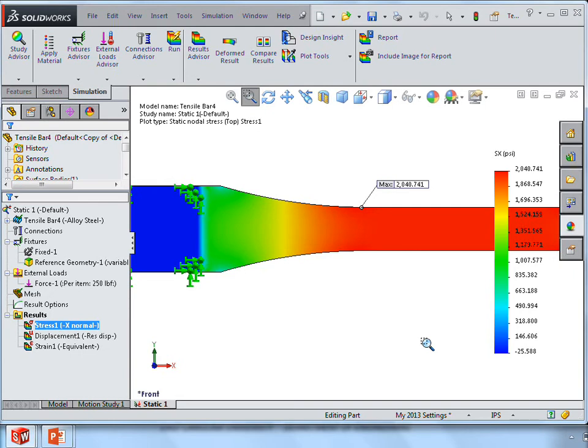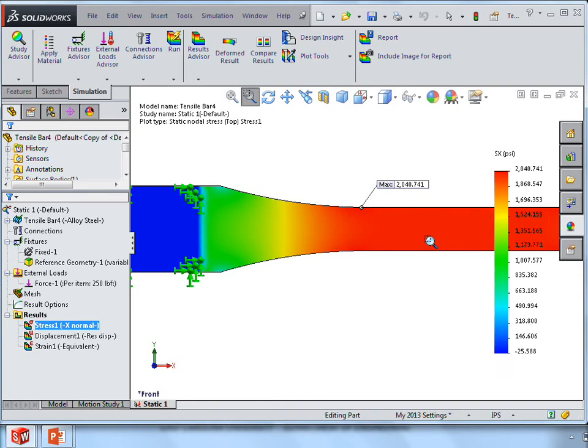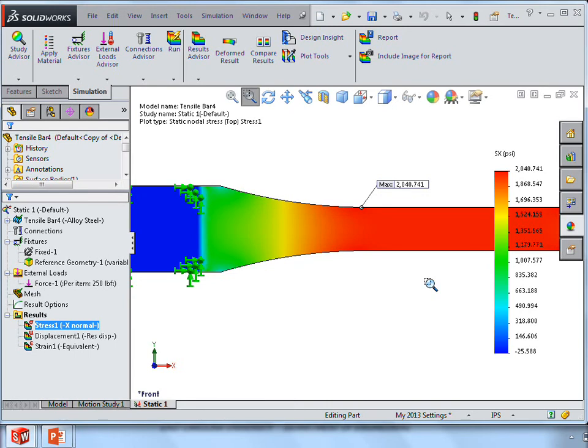And remember, if we're testing a ductile material, one that stretches a good bit before failure, even if there's a slight stress concentration, we'll get some local yielding which will allow the stresses to redistribute to the area near it. And so we still should get failure out into this region, out into the area of constant stress. And if we make that area long enough, then we can put a strain gauge out in that middle portion. We can put an extensometer over that middle portion, because as long as we're far enough away from any stress concentrations, then our stress state can be assumed to be constant within that region.